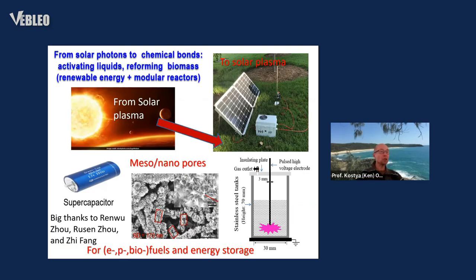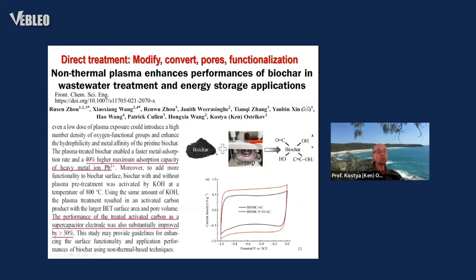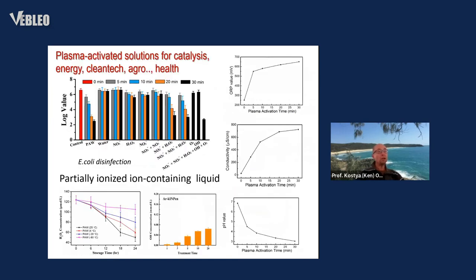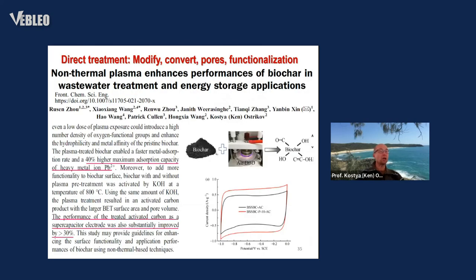Let's consider first a treatment in the dry, in the gas phase. The same discharge which I showed you before was used to treat biochar, a common byproduct of agricultural industrial activity. And just by simple treatment by plasma at atmospheric pressure, biochar becomes more active in two very important applications for sustainability, for storage of renewable energy in supercapacitors, and also by absorbing some harmful contaminants from the water. Another area of application, as I said, this was the dry processing.